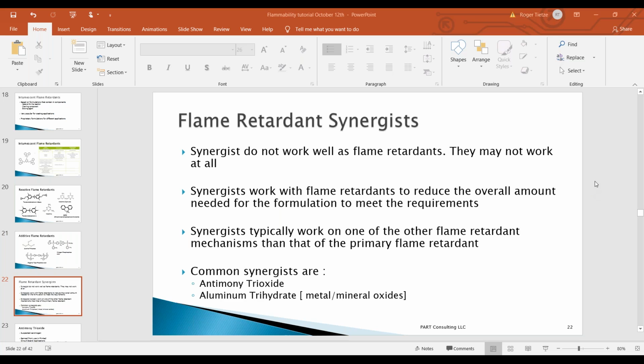One thing also is there's still a lot of applications today that will utilize, with the flame retardant, the synergist. And synergists basically work with flame retardants to reduce the overall amount needed for the formulation to meet the requirements. Simply put, if you have 20% bromine in your formulation to get V0, by adding antimony, you could reduce that amount all the way down to 12%, 10% bromine. And there are reasons to use this. It makes the flame retardant more effective, it saves costs, and it may even improve the properties.